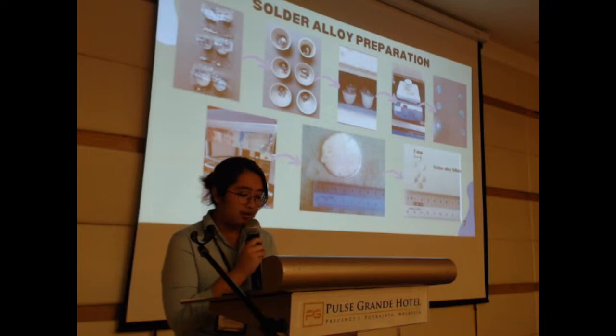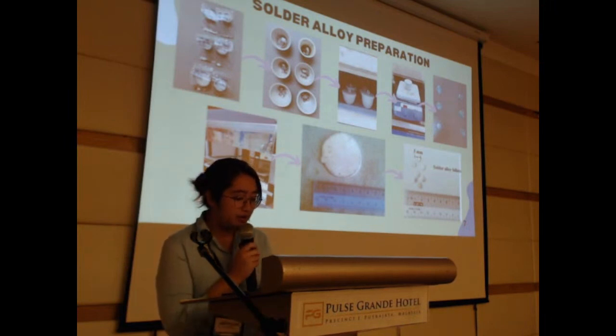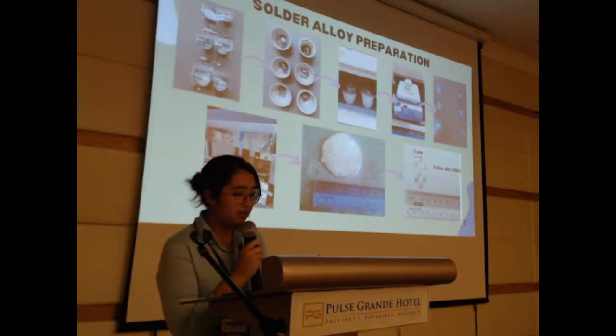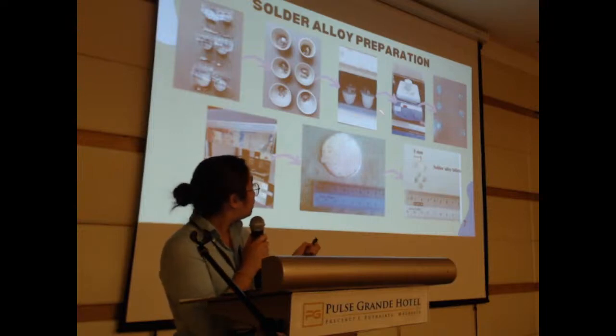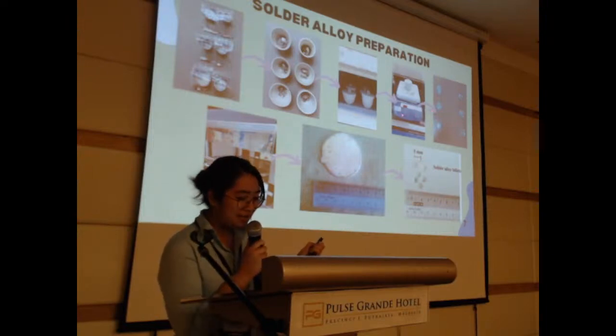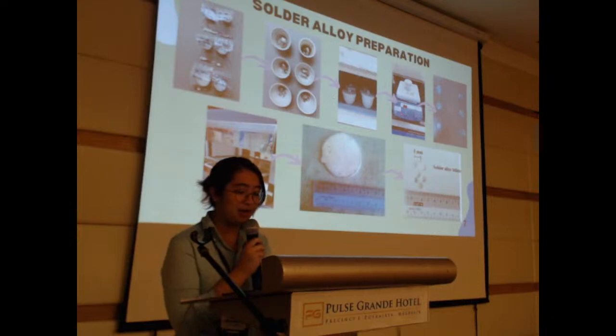So as you can see here, these are the sequence of solder alloy preparations. It starts with weighing the tin and bismuth according to the bismuth compositions. Then the metals are heated in the furnace to about 400 degrees Celsius, held for about an hour, then cooled down. And then it goes through the remelting process where the solder will be placed on the hot plate